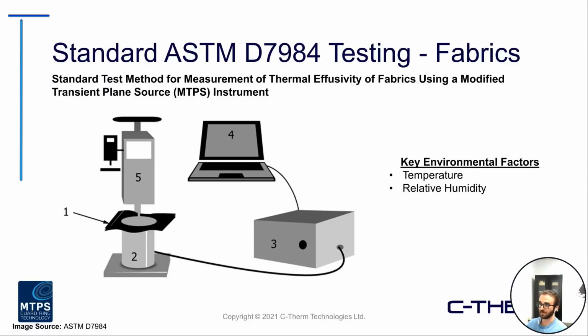So starting out, I just wanted to give an example of some standard ASTM D7984 testing of fabrics. This method is the standard test method for the measurement of thermal effusivity of fabrics using an MTPS instrument. As written, this standard provides a lot of guidance on the setup requirements and the overall parameters that you need to use for the measurement. You can see in this little graph here, you have the different components. You have your laptop connected to your controller device, which then feeds into the MTPS sensor, and in this example, inside of a compression device with the sample layered on top.